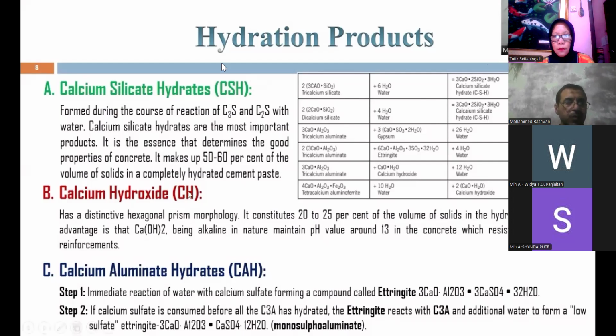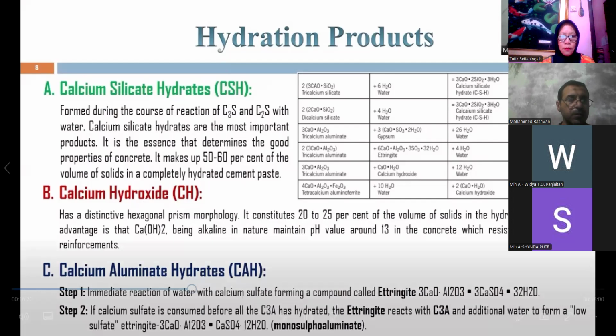The other percentage is represented by calcium hydroxide, which is the second hydration product. This phase consists of about 20 to 25% of the volume of the solids in the hydrate. And this phase may decrease. How can the calcium hydroxide decrease? If we add some additive materials, especially inorganic materials, they react with calcium hydroxide to liberate CSH again.